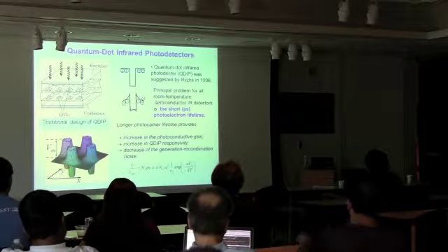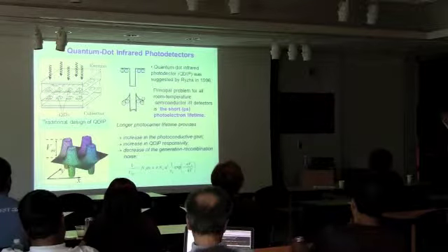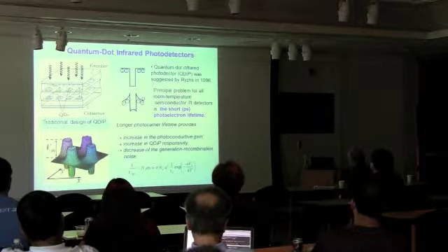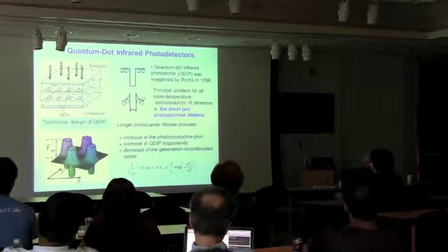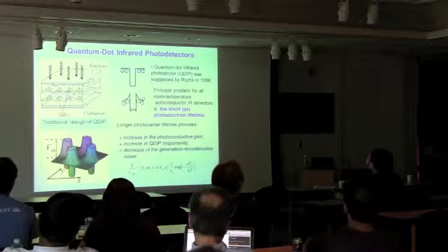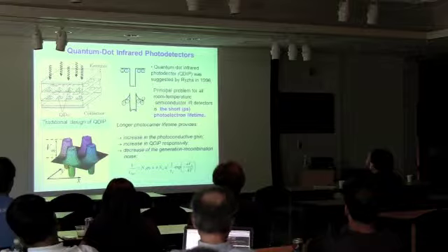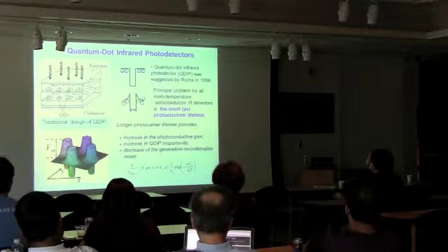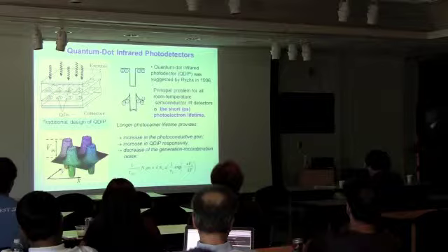And as it would like to have the electron back, you really increase the probability for the electron to recombine, yeah? So what we suggest is that you need to dope this material outside of the dot. As you have impurities here outside of the dot, then electrons go to the lower energy and populate the dot. What is going on? The dot is now charged negatively, the surrounding is charged positively, and you have something like